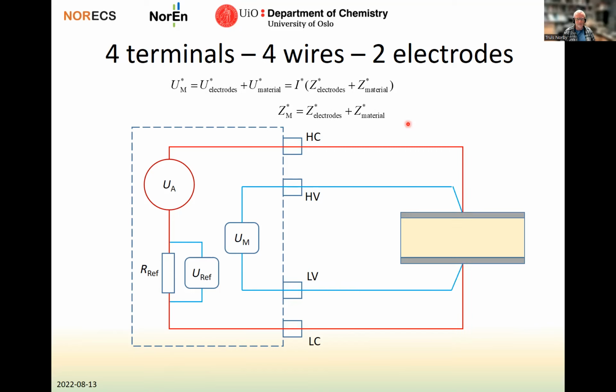We can go one step further. We can have 4 wires all the way up to the sample. Then we also get rid of the voltage loss in the wires, because now we measure the voltage here and there is no voltage loss in these wires because there's no current running here. So now with a 4-wire 2-electrode measurement, what we get is only the impedance of the electrodes and the material.